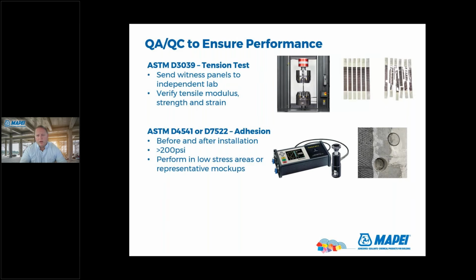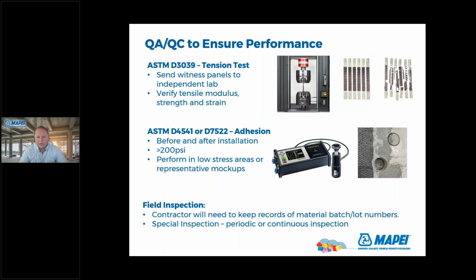And then you're going to want to make sure you test this in areas that are kind of low stress. So if you are putting up FRP on the bottom of a beam to increase the flexural capacity, you don't want to test it right in the middle of the beam where the moment's going to be the highest. You want to do it on the side. And so that's the common testing that we see.